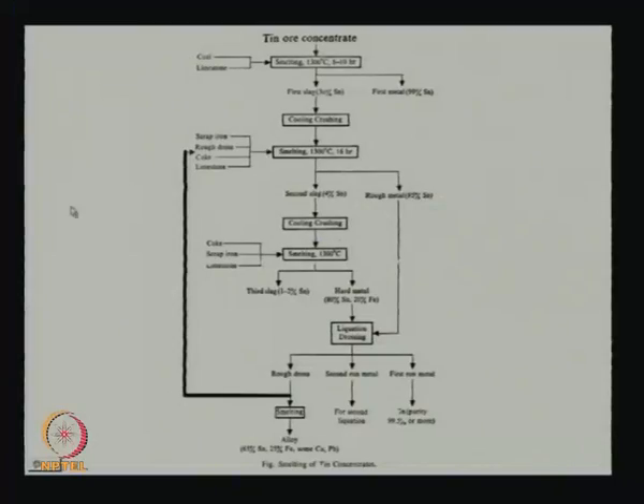If you want, we can reduce it. If you make it more reducing condition, if you add more carbon, if you allow more time, tin will come out, but iron will also come out. We do not want that. Initially, we allow an incomplete smelting precisely because we want the first metal to be as pure as possible, and we might get as much as 99% tin in that step with only 1% of impurities, slightly different from what I had mentioned a bit earlier.